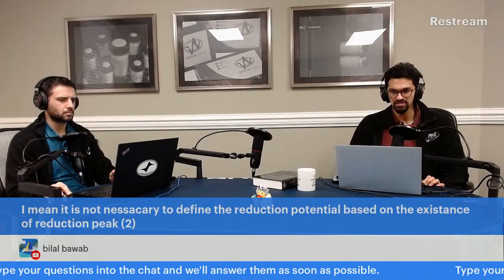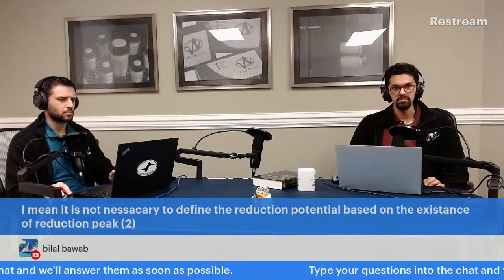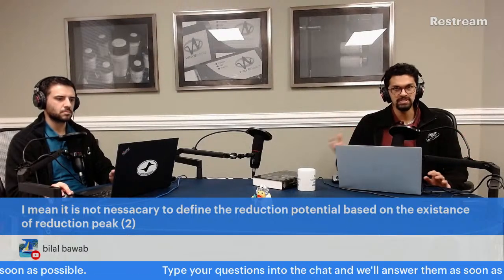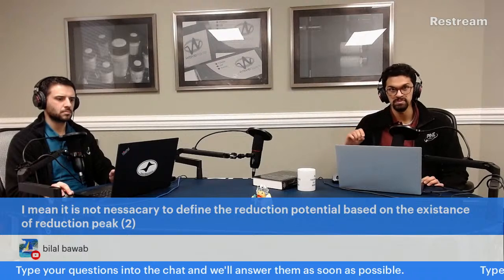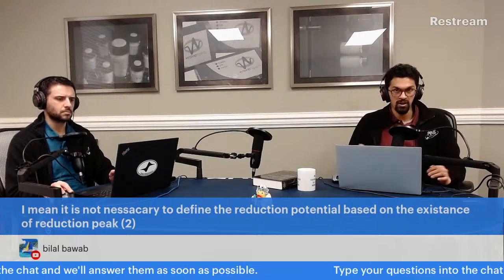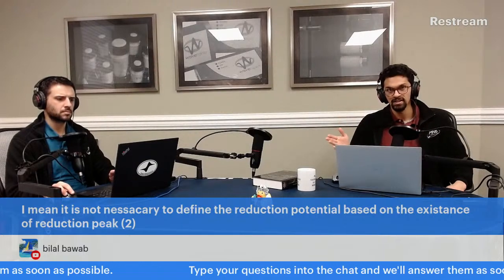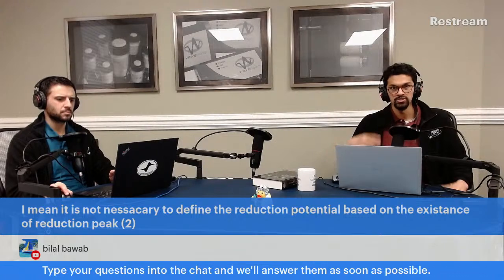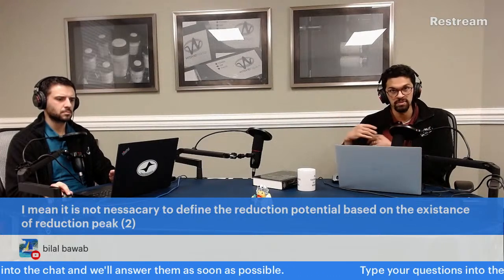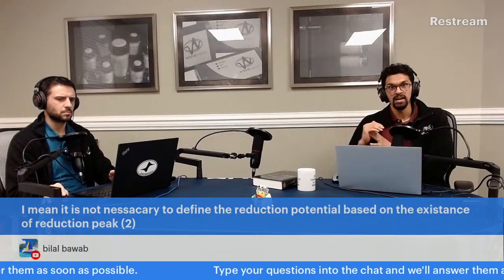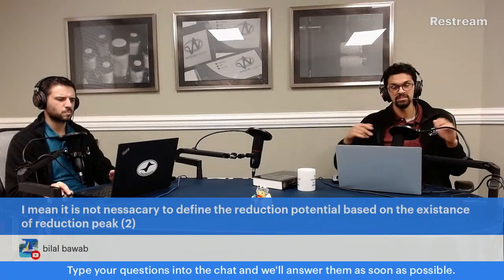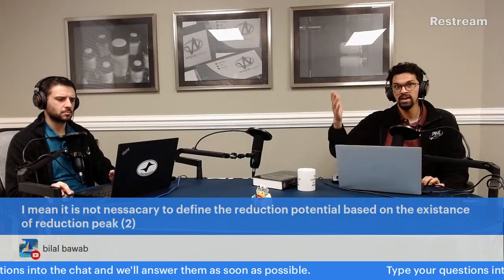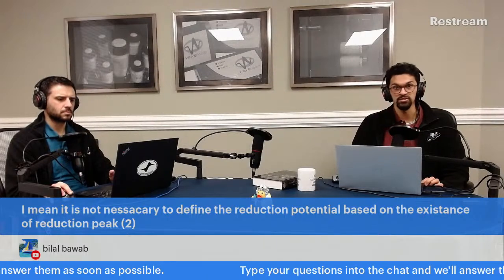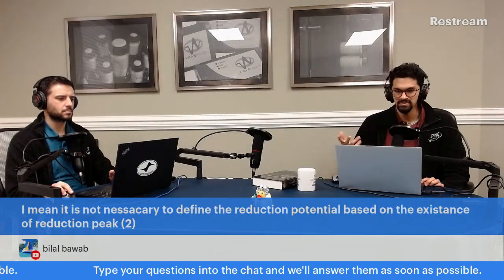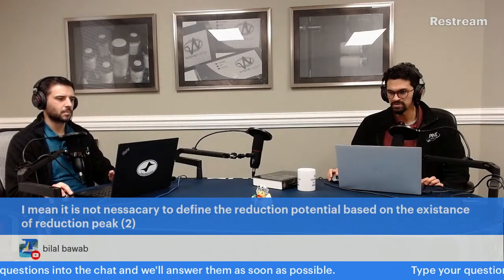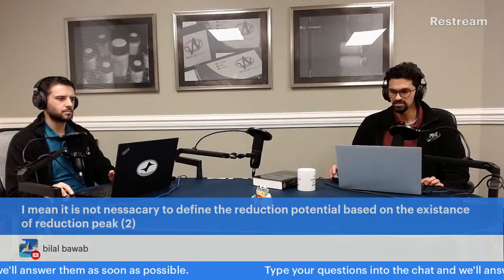So the experiment that you may need to do is, after you do the deposition and maybe you don't get any peak data, you might need to polish or clean the electrode, maybe pre-treat it, so that that layer is no longer on the electrode surface. Then when you put it back into your electrochemical cell, make sure you're at a very positive potential so that no reduction occurs. Then as you sweep the potential, you should see a peak associated with the reduction of that metal cathodically onto the other metal. That's my hypothesis, at least, without knowing any more details on your system.